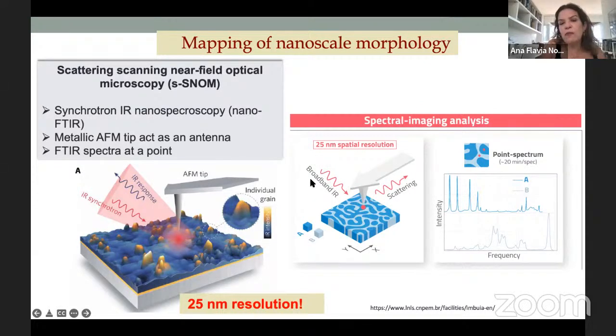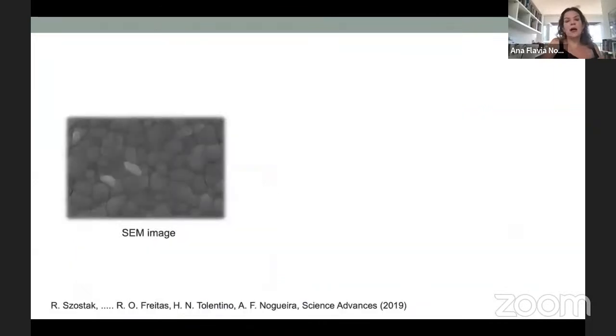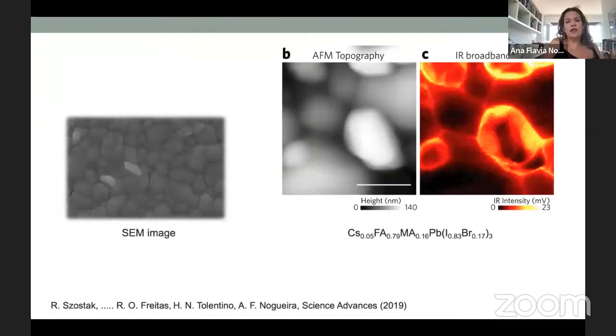You can have the image, what we call a broadband image of your sample, but also you can get the point spectrum. It means that you can just choose one grain, one point here, and you can have an infrared spectrum of that point. Of course, this is a complex technique. I would need much more time to explain the details, but I just want to show how powerful this technique is for other materials instead of the perovskite.